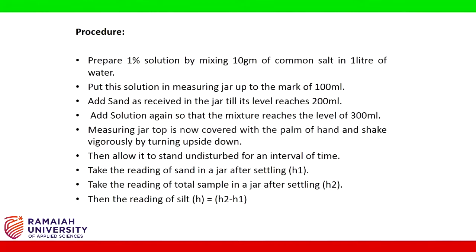Put this solution in the measuring jar up to the 100 ml mark. Add sand as received in the jar till its level reaches 200 ml. Then add solution again so that the mixture reaches the level of 300 ml.